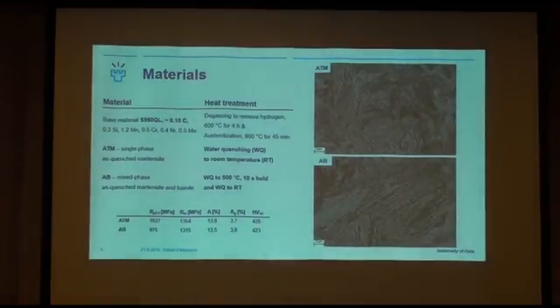I made two different microstructures from S960QL steel plates. First, a single-phase martensite, and mixed-phase martensite and bainite. And the essential difference between these two is the precipitation morphology and where they are in the microstructure. As you see, the yield strength of these steels is around 1000 megapascals. They have sufficient ductility and quite high hardness. And these are used in this condition in weight critical applications, like mobile equipment and so on.